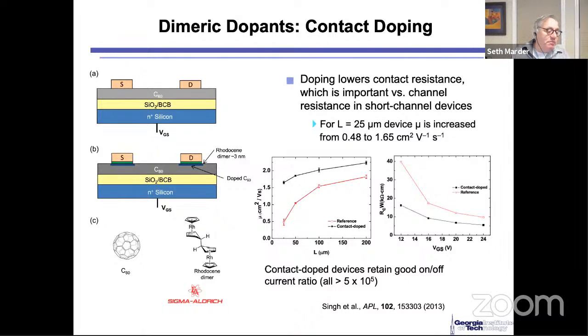In one case, we changed everything, and that may have varied the contact resistance. But in this case, what we tried to do is only vary the contact resistance, without changing the material within the channel. Another point worth noting is that in the first example, we tried to not substantially change the conductivity of the system. Here, by virtue of the dopant being in contact with the C60 underneath these contacts, it is pretty heavily doped. Only under the contacts it's heavily doped, but in the channel it's not.